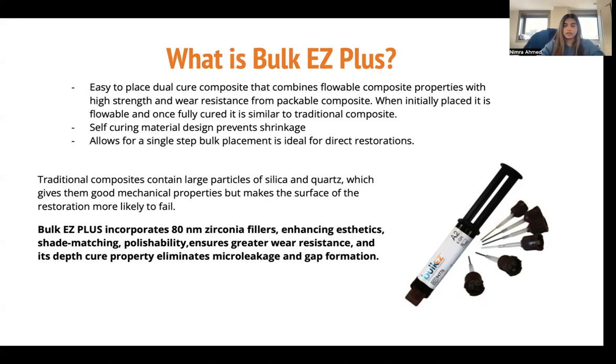Traditional composites contain large particles of silica and quartz, which give them good mechanical properties but make the surface of the restoration more likely to fail. With Bulk EZ Plus, it incorporates 80 nanometer zirconia fillers, which enhance aesthetics, shade matching, polishability. It ensures greater wear resistance, and its depth cure property eliminates micro leakage and gap formations.